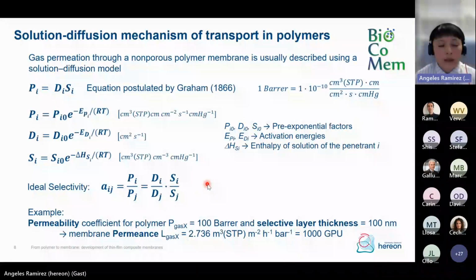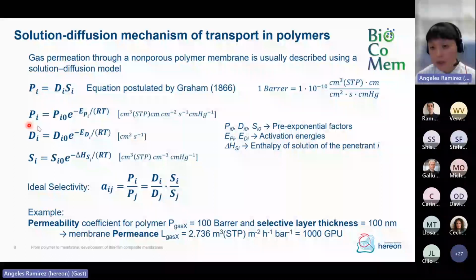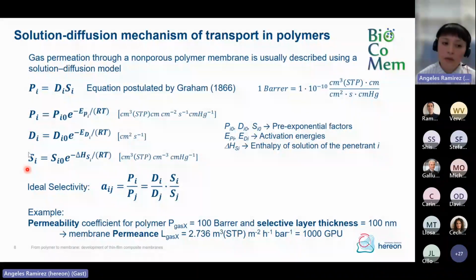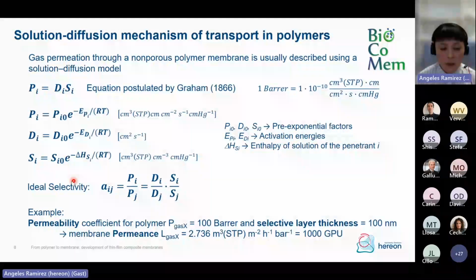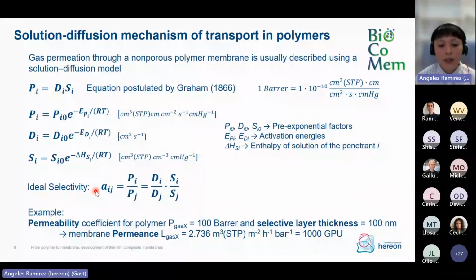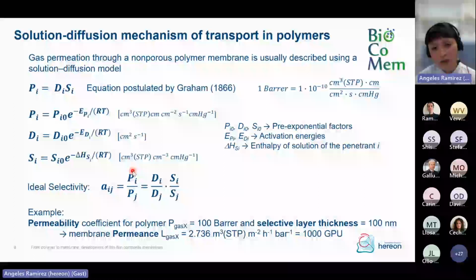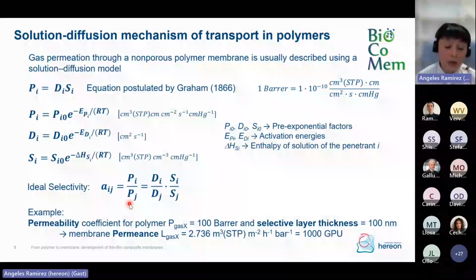Now, this whole process, as you can see here, is a thermally activated process. And from this, we can expect, for example, that the diffusivity will increase with increasing temperature and the solubility will decrease with increasing temperature. Another very important parameter is the selectivity for a given gas separation, which will be defined by the ratio of the permeabilities of the fastest to the slowest permeating gas component.